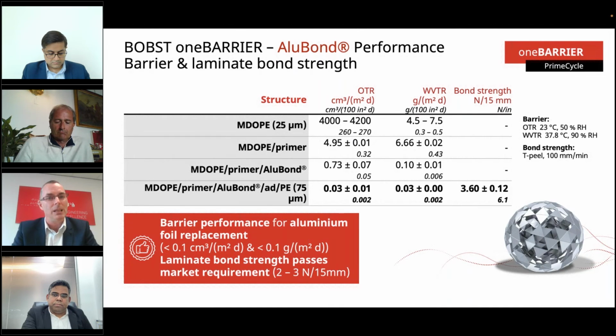If we now take a look at the opaque, shiny Alubond metallized solution, and again look at the performance through all conversion steps, we have the same base film, but in this case, we use a different metal receptive primer for the Alubond. And with the primer, we can enhance the OTR to around 5 cc's, again with no improvement in WVTR.